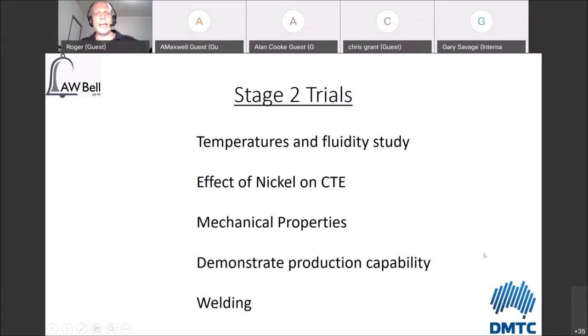So the stage 2 trials, and so this is looking at some effects of temperature and fluidity. Now, of course, one of the things that we want to do with casting, we want to cast it as cold as possible to get a good result. This is one of the fundamental things of casting. You don't go too hot, but you've got to be fluid enough to fill your mold. So we looked at the effect of nickel on the coefficient of thermal expansion, and this was based around suspicions that the result that was being seen in the Boeing specification alloy were associated with the nickel content. Some mechanical properties, that are just standard tensile properties, and then moving on to demonstrate production capability, and also welding.